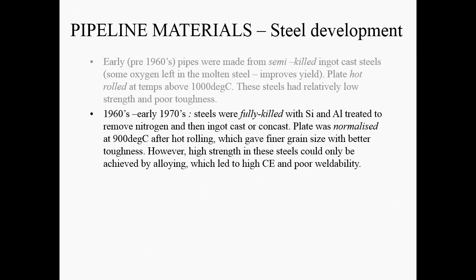And you could do that by reheating. You can hot roll, cool to room temperature, and then reheat to above 900 and cool, because undergoing the phase transformations on cooling and heating will help to refine the microstructure. So that was a very good steel, better toughness because of the small grain size largely, but still not particularly strong.